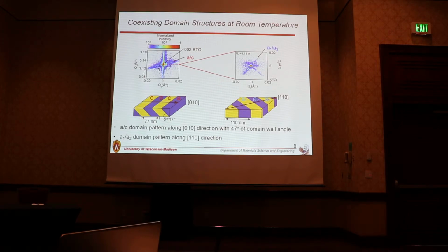So this figure shows the QZ, QY plane, including the 002 barium titanate reflection and its thickness fringes along the QZ wave vectors. You can see AC domain patterns arise along the 010 direction, which means these AC domain patterns are aligned along the 010 direction. We measured the domain periodicity and domain wall angle, which are 77 nanometers and 47 degrees respectively.